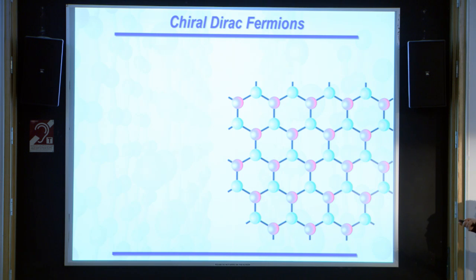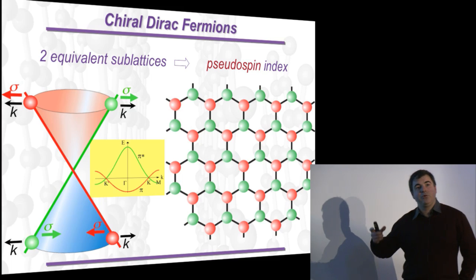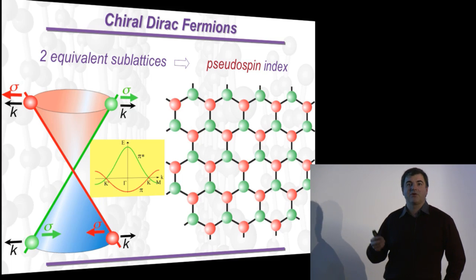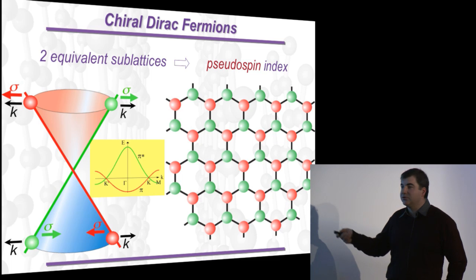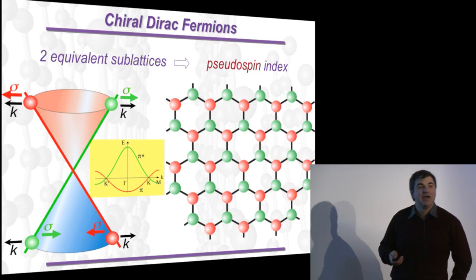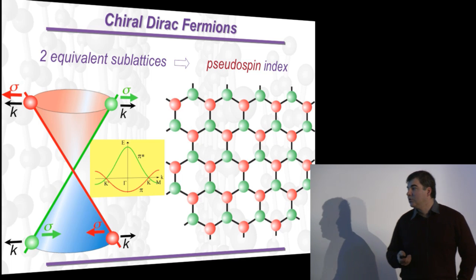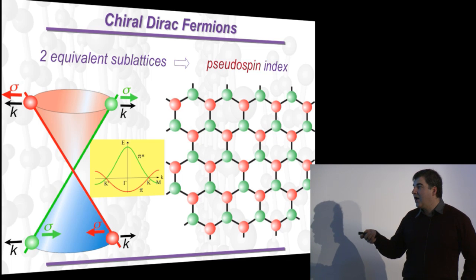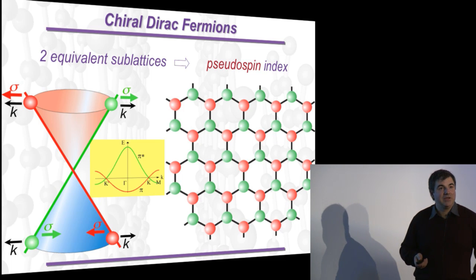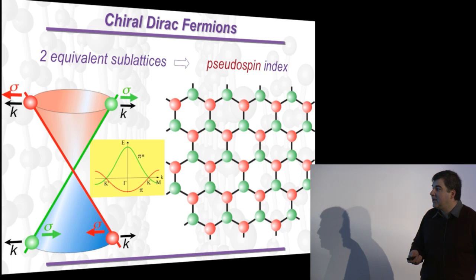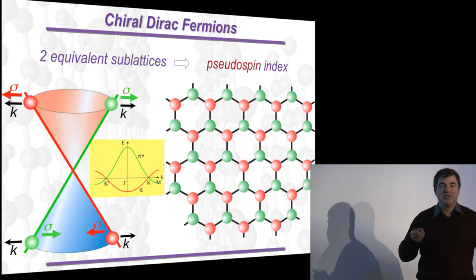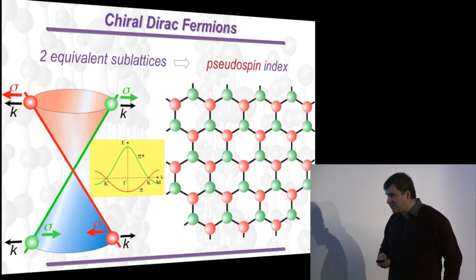Say all the red would have a neighbor from the bottom, and all the green would have a neighbor from the top. Because we have 2 atoms per unit cell, we always have to play with combinations of two electrons which are living on those two sides, on the green and on the red side. And because we have to play with those two, we create two energy bands which are crossing at two very special points of the Fermi surface, and this gives us the linear dispersion relation for our quasi-particles.